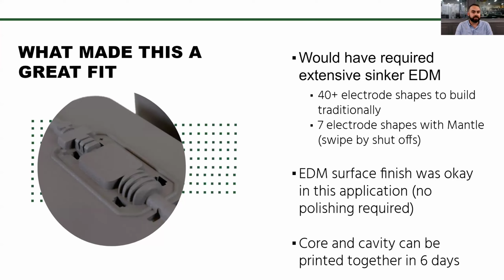The other big thing that was a huge benefit that made this a great fit was that the off-the-printer surface finish was okay. We didn't have to do any additional polishing or anything like that, which helped condense your lead time. So if you have anything where they're looking for like a C1, a B3, this actual part, the 2D print, was calling for a C1.